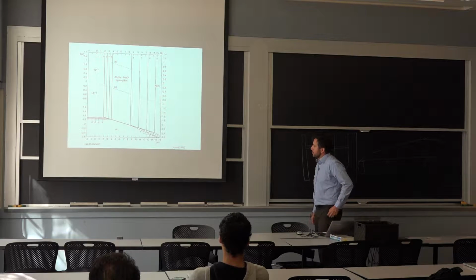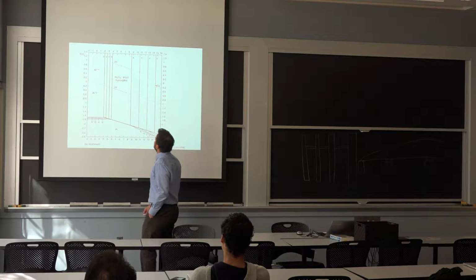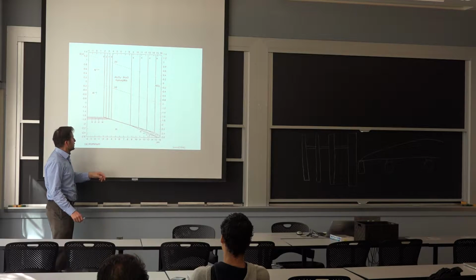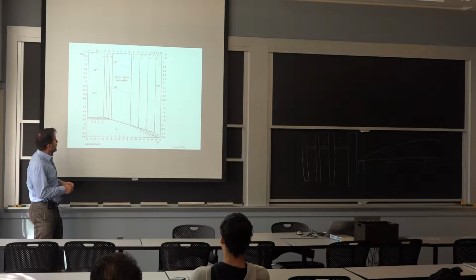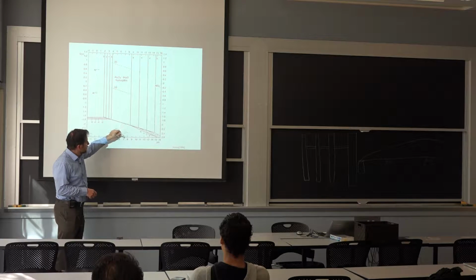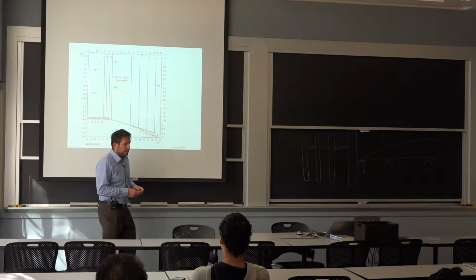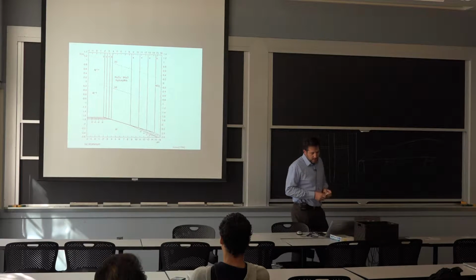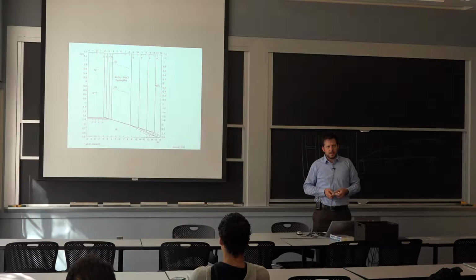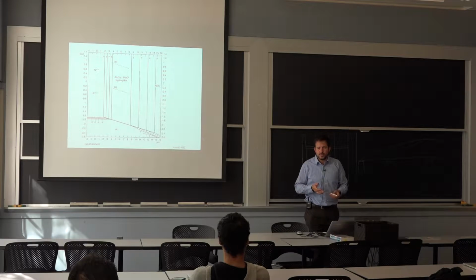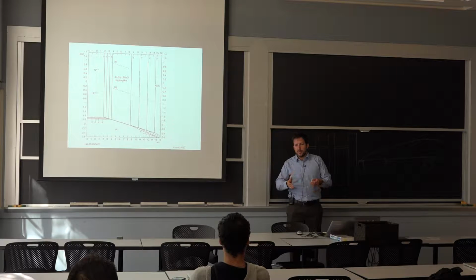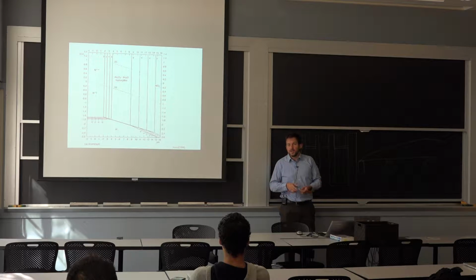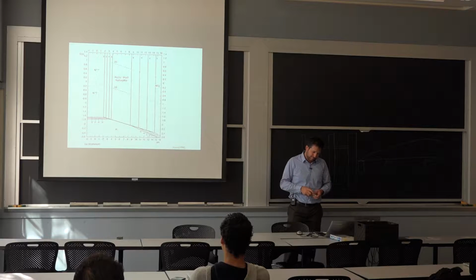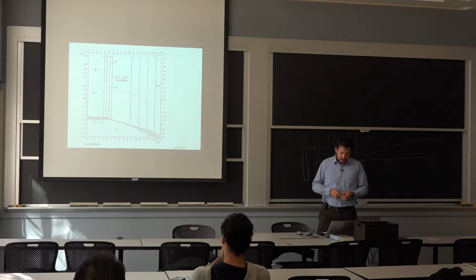I mentioned this earlier, I'll bring it up here again, that with aluminum, we were saying we don't have a whole lot of issues with corrosion because the alumina on it is very stable, but this is a very precise stability zone for that alumina in service. So if you have an acidic environment, the aluminum will do very, very poorly. Somebody last year in their project wanted to use aluminum for a special application, and they were surprised that it was corroding. So I had them check exactly what the liquid was that they were using in that tank, and yeah, it was pH 2. So there you go. It didn't last.